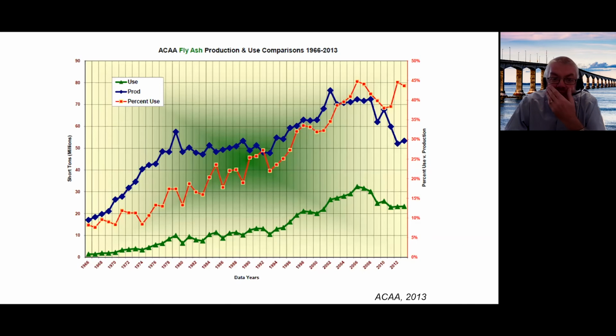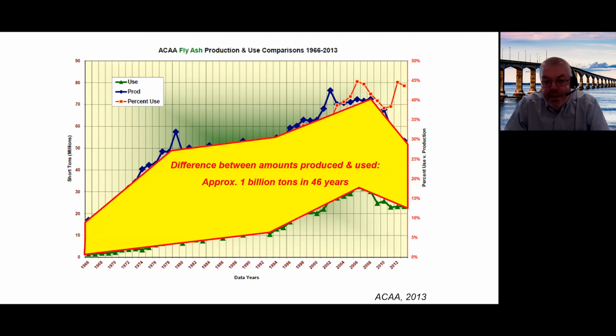So if we look at this graph here, this is a graph dating back to 1966. And if we integrate the area between that blue line, the amount of fly ash produced, and the green line, the amount of fly ash used, I just did this as a quick calculation, then in that 46-year period, there was about 1 billion tons of fly ash that have not been used, and have presumably gone either into lagoons or landfill sites. Now, I'm not saying all of this fly ash is usable, far from it, but a good portion of this fly ash we can expect to be usable in concrete.